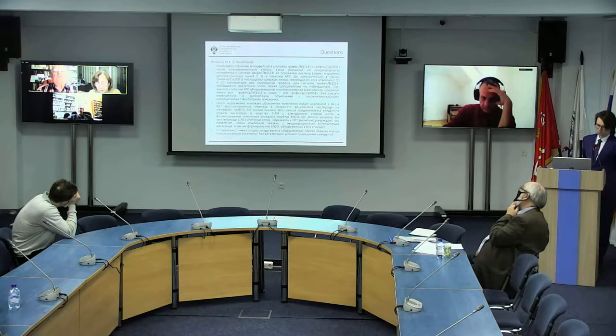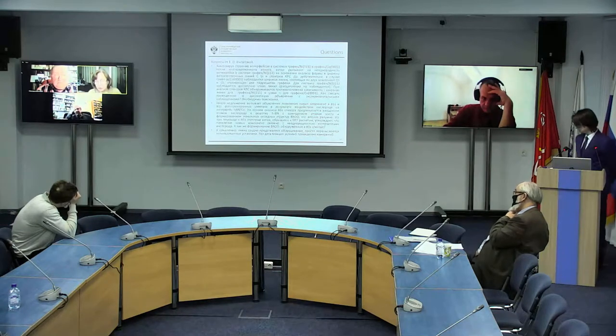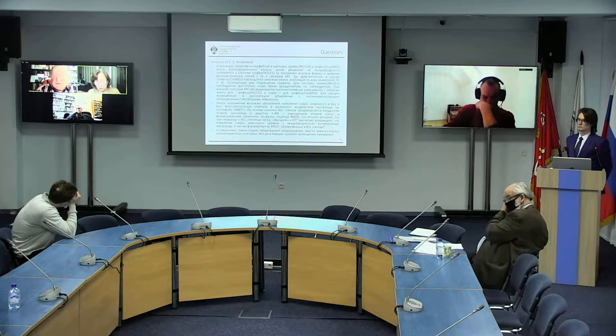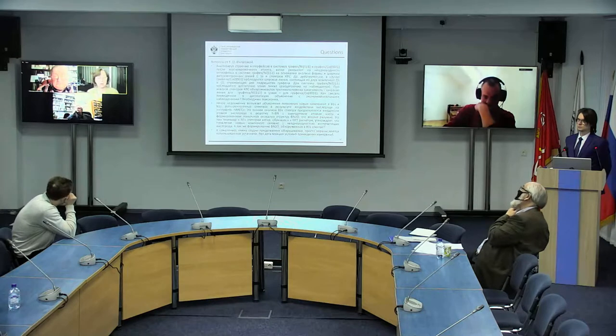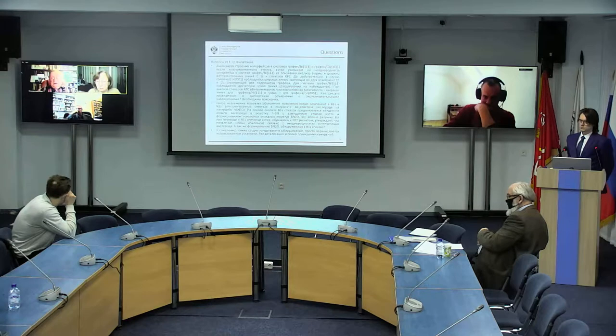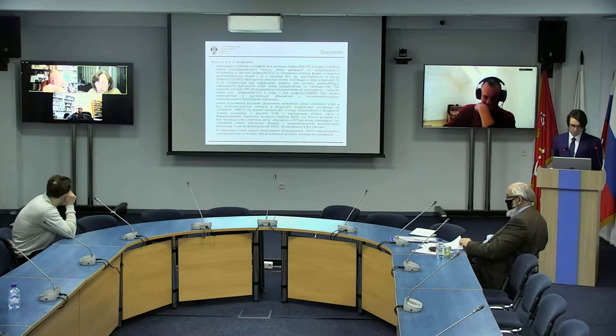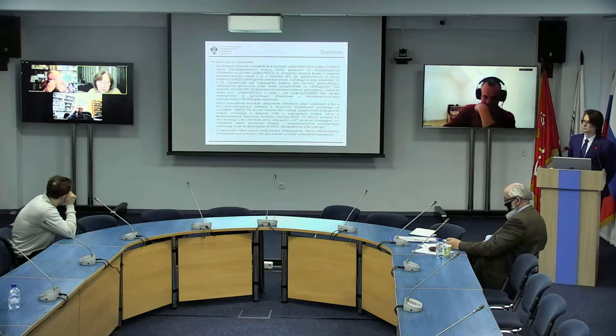Third point. It's unclear how you explain the emergence of new components in the boron and nitrogen spectra under the impact of oxygen on the interface of hBN on cobalt. Based on the analysis of the boron spectrum, I presume that there's an introduction of oxygen atoms into the lattice of hexagonal boron nitride with a substitution of nitrogen atoms and the formation of local oxide groups, BN2O, which is quite probable. But when we shift to the nitrogen spectrum, the author, using DFT calculations, says that the emergence of new components is associated with heterogeneity of intercalation of oxygen. And what about the formation of BN2O that we see in the boron spectrum?